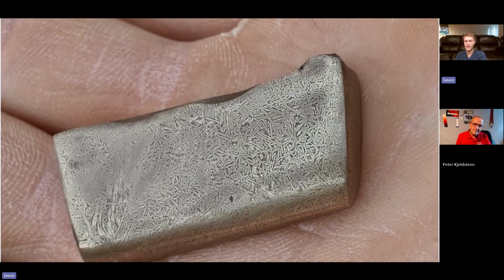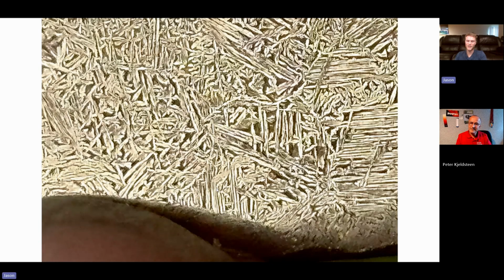And so that's what you see here. If we take a closer look at this, sorry, not a macro lens, just zoomed in with my phone camera. Your phone? Yeah. Wow. And this is my fingernail. So, I mean, it is pretty small still. And so you can kind of see, this is probably a grain. This is probably a grain. This is a grain. And you can see that these alpha plates all have a common symmetry within their own grain. If we look from this grain to this grain, the directions that the alpha plates are going are different, because the grain has a different crystalline lattice direction. It's shifted in some sense. And so the preferential growth directions macroscopically are relatively different.